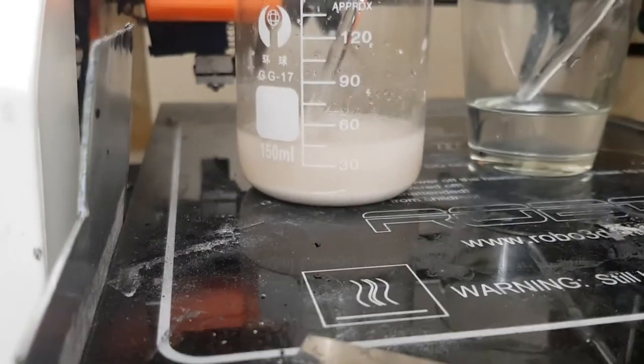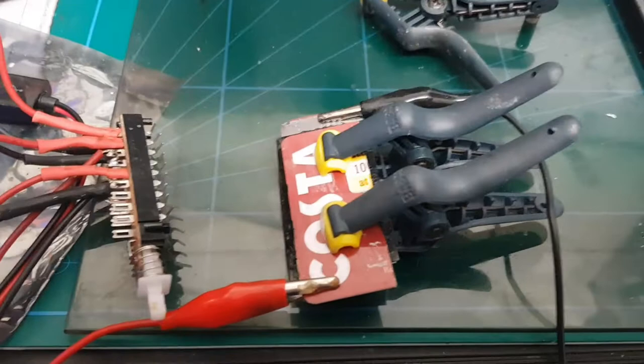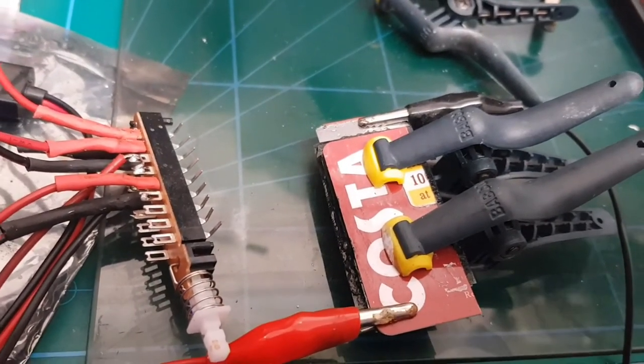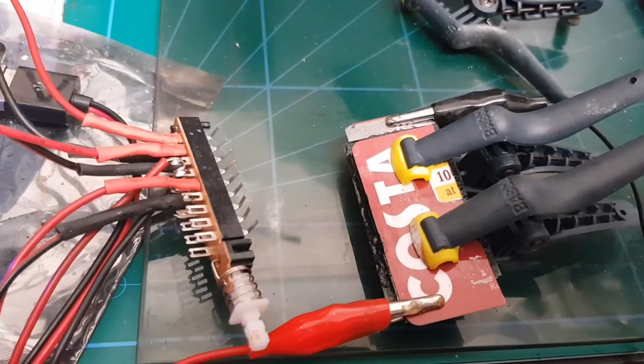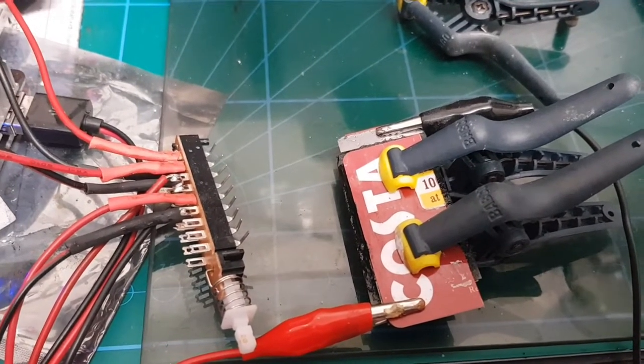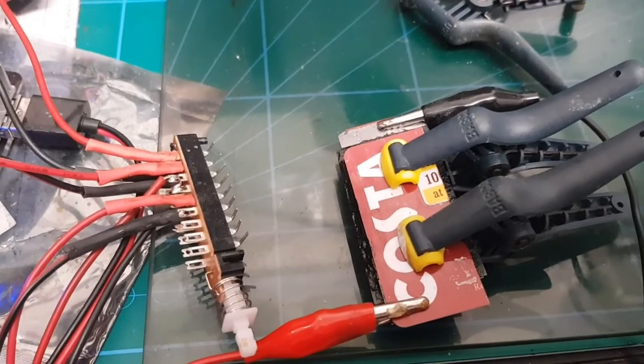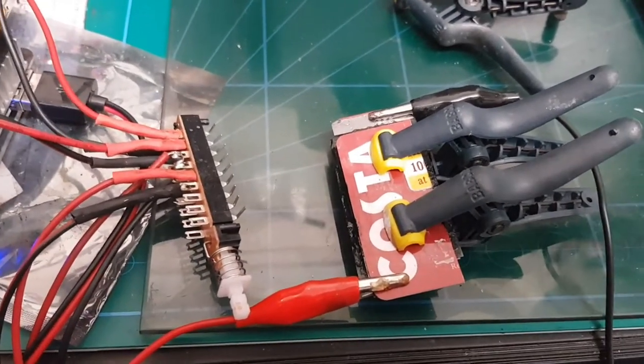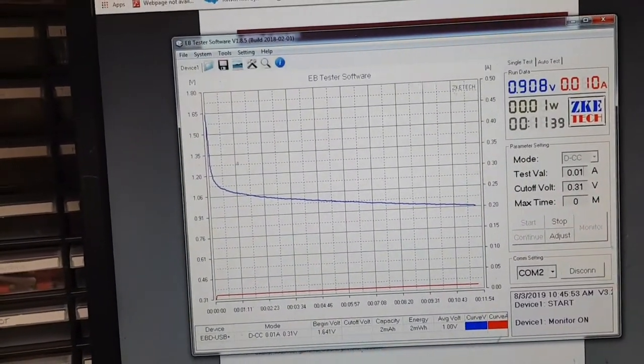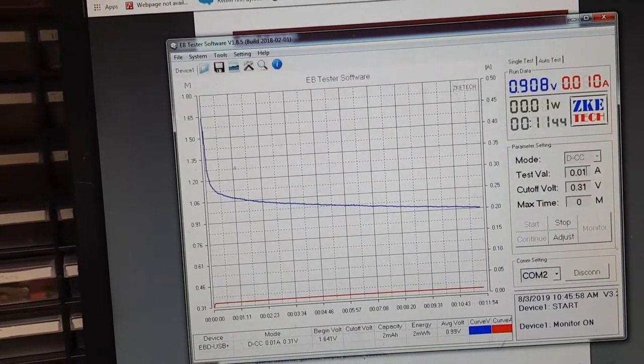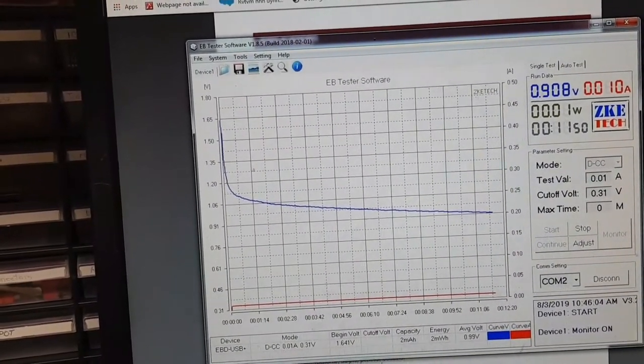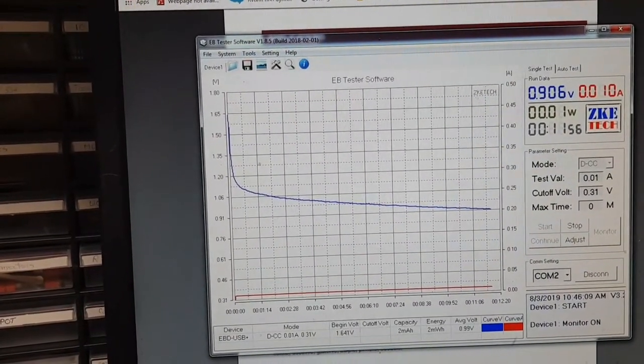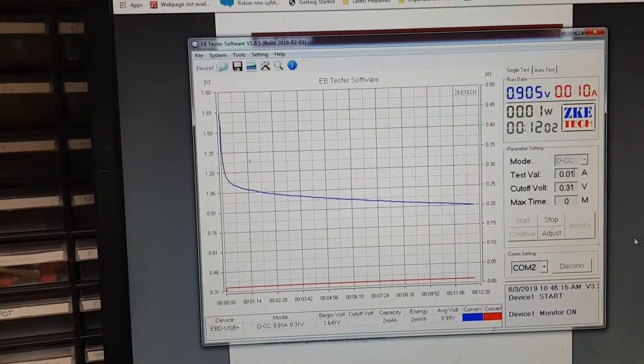I'm already testing here a symmetrical supercapacitor construction device, all carbon with normal filter paper separator. The total weight on both electrodes is 0.5 grams of active material. It has the choline chloride deep eutectic solvent as electrolyte. The discharging curve shows 11 minutes at 0.9 volts. It dropped from 1.6 to roughly 1.2 initially, then became very stable. It's discharging at 10 milliamps.